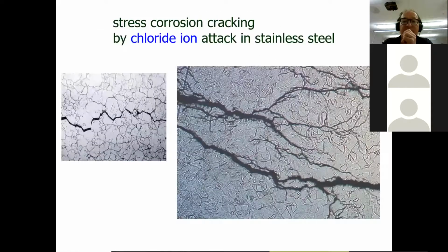So let's have a look at some micrographs. Under the electron microscope or even an optical microscope, you'll see this effect. You can see the cracks. These dark lines are indeed the cracks between the grains. These are the grains, and these are the cracks, the darker lines. This looks like a river flowing through a valley. It almost looks like a satellite photograph of the Earth, actually. But it's not. This is a microscope picture. And you can see the cracks here, and you can see they're following the grain boundaries if you look carefully enough.